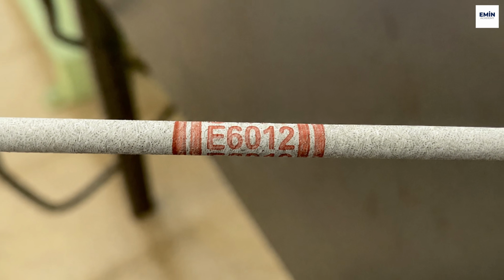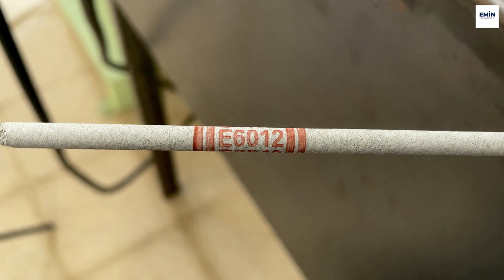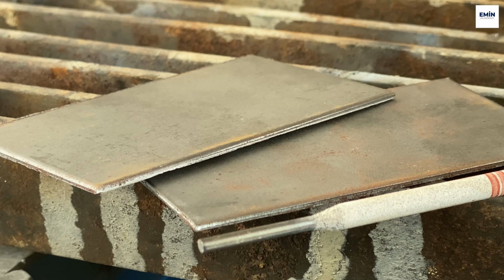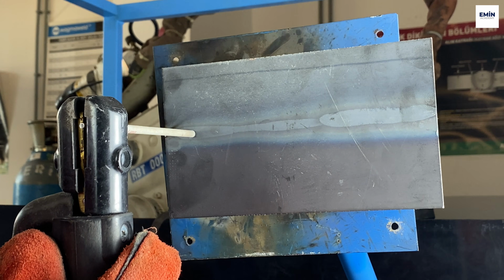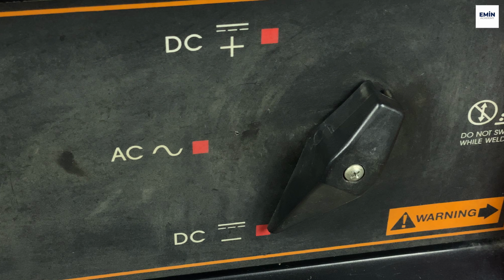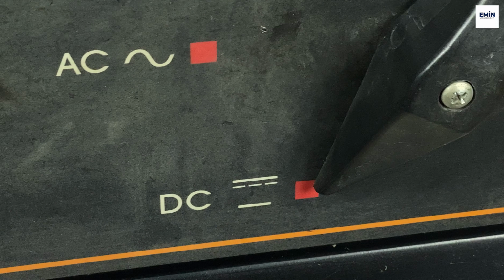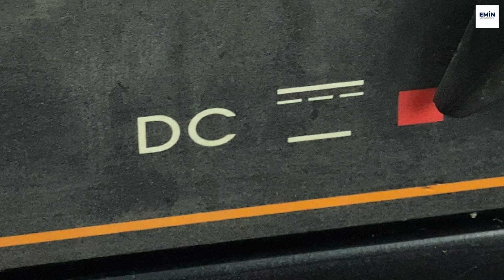2. Rutile-coated electrode. The E6012 electrode is an example of this. It provides medium penetration. Its arc is softer. It's generally used on thin sheets in horizontal and flat positions. It's suitable for alternating current and direct current electrode negative polarity.